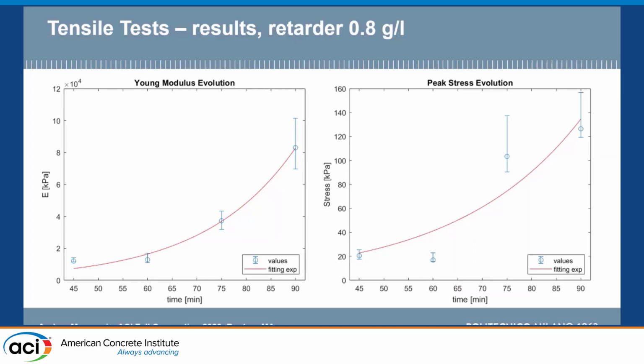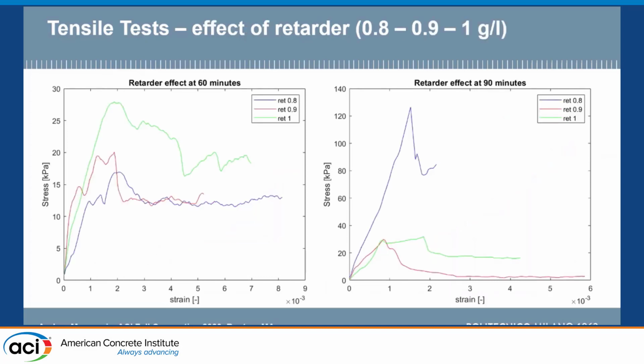In fact, at the beginning, the strength is not increasing, so there is a flat increase, and then an exponential increase of the strength, both looking at the Young modulus and the peak stress. And this is the influence of the retarder. So it seems now too early at 60 minutes to see any effect of the retarder on the strengths, whereas we can see instead at 90 minutes the effect of the retarder.